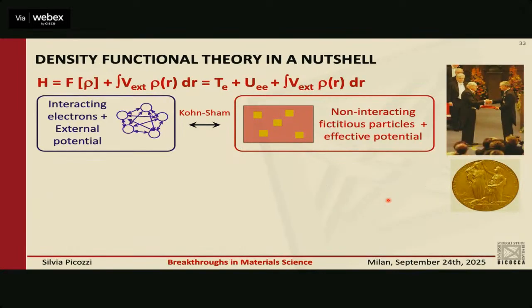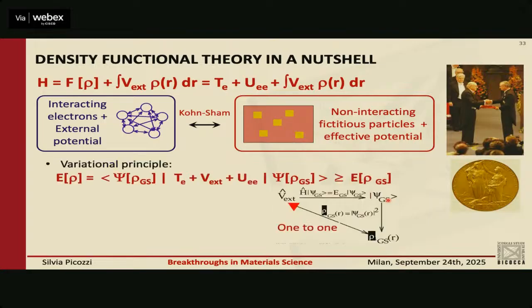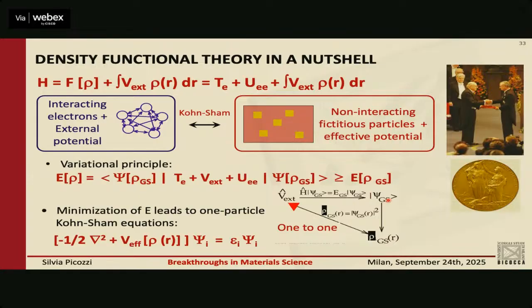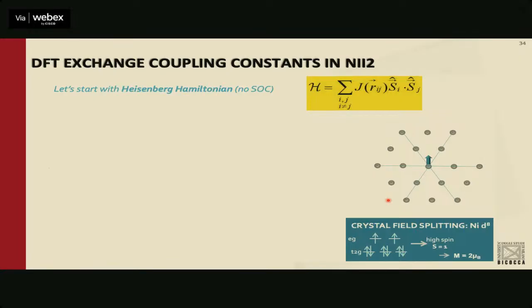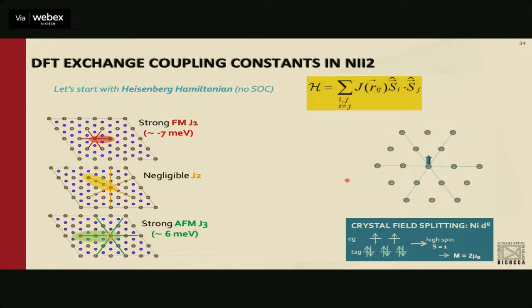Okay, this I guess I can skip. There's a big community of density functional theorists here in the audience and in the department, so I guess I can skip this. But by density functional theory, you can estimate from first principles the exchange interaction, which is what we did for nickel I2. And so if we do that for nickel I2, what do we get? You have a strong ferromagnetic first nearest neighbor J, a negligible second nearest neighbor, and a strongly anti-ferromagnetic J3.